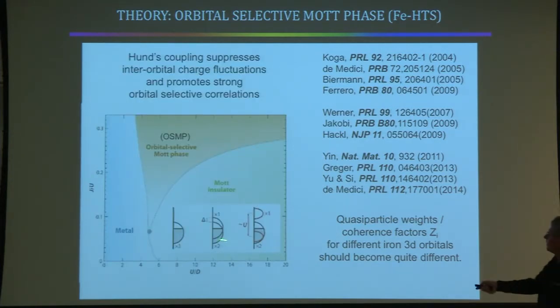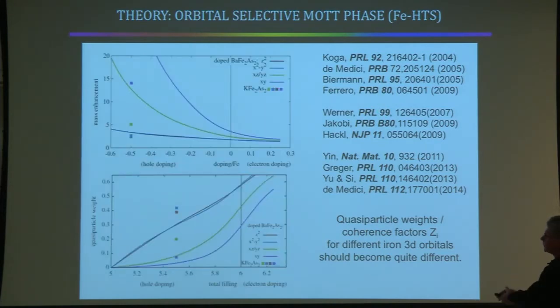Now, when this happens, DMFT calculations show that as a function of doping, you can alter the degree of orbital selectivity. So this is for an iron-based superconductor, and this is the quasiparticle weight. For some orbitals, and now I'm colorblind, so I can't read this thing, the quasiparticle weight collapses very quickly as a function of doping, and for other orbitals, it remains robust as a function of doping. There's a simple way of imagining that.